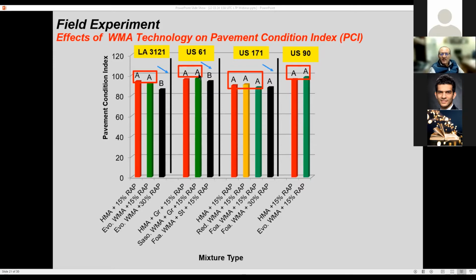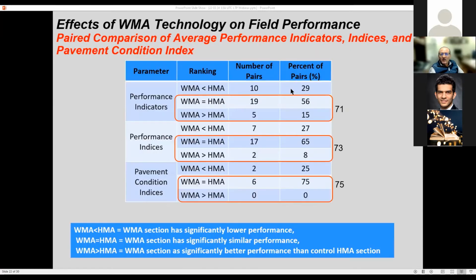Similarly, in these other sites, US 61 shows similar results in these particular systems right here. Now, some of them had slight variation, not only in the content of the additives, but also aggregate types. So this could be a contributor as well. When you deal with field conditions, sometimes that's what you get. And looking at US 171, that's our best controlled experiment. You see the effect of these various additives and the effect of RAP, as well as the one on the US 90 system.